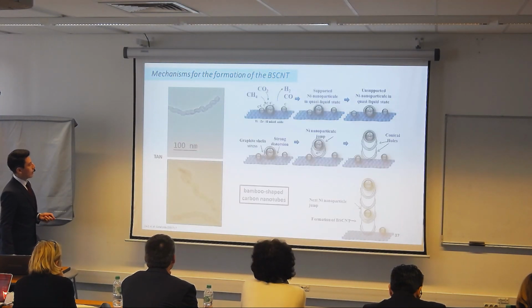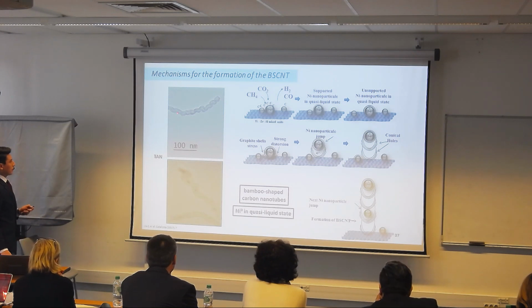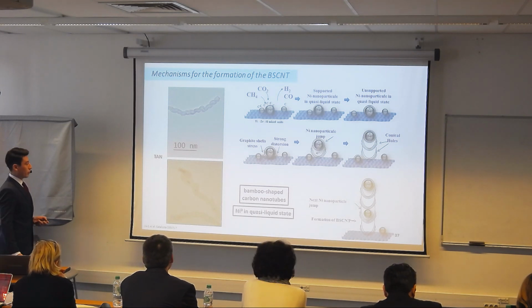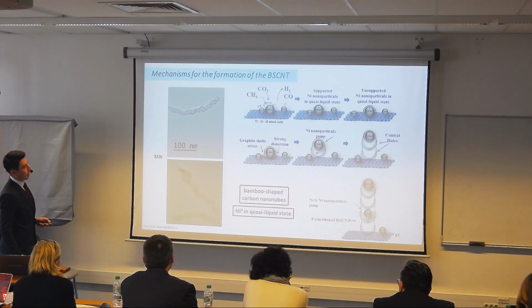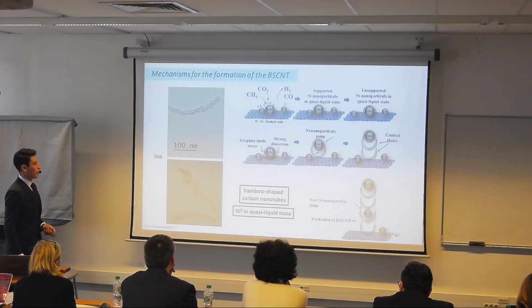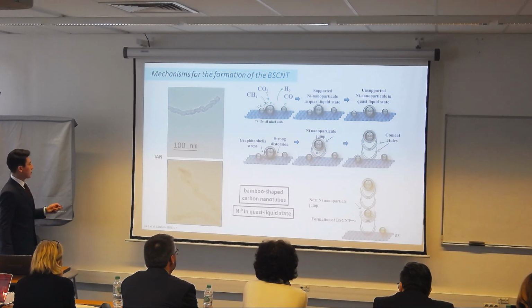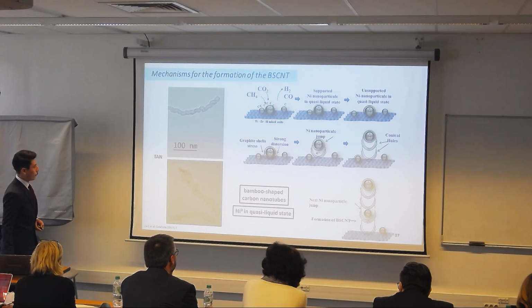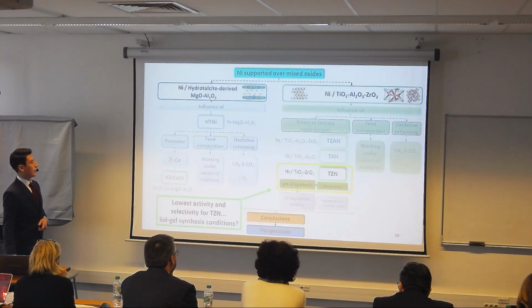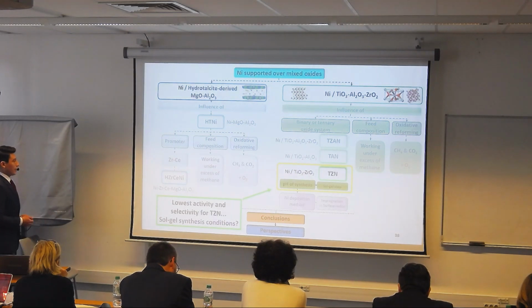So we wanted to explain what is happening in the formation of these bamboo-shaped carbon nanotubes, and I propose here a mechanism for their formation. It's mainly due to the quasi-liquid state of the nickel through the reforming reactions. Here you can see an example of the TEM for the TZN catalyst. We find that this catalyst containing zirconia is the least active.